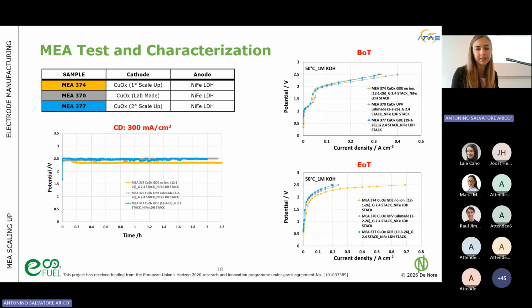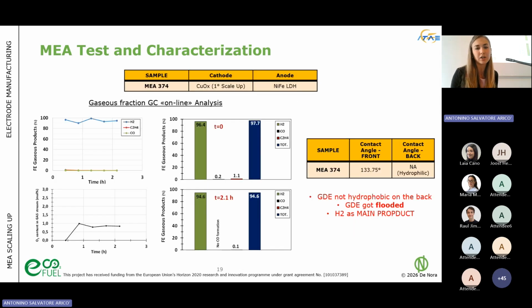Also looking at the graph at the end of the test. But then what could also happen in this case is that we are actually producing just hydrogen, and that's the problem of the cathode that we saw, because by looking at the contact angle of the GDE, we discovered that the back side of the GDE is completely hydrophilic. So actually, just at T0, at the start of the test, the electrolyte is flooding the GDE. So it's basically just doing hydrogen. It's just getting water, and the only thing that it can do is hydrogen. So that was the problem that we encountered.